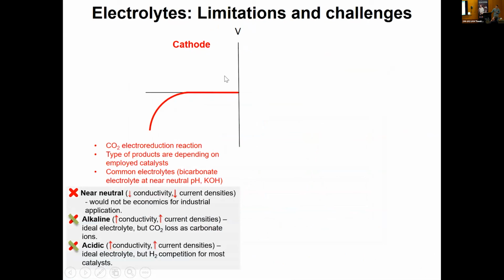So if you look at the limitations and challenges on the reduction part, where the CO2 reduction happens, near-neutral is mostly not economic for industry because it has low conductivity and low current density. If you want to compete with the established methods, that's a challenge. But alkaline electrolyte really shows good high conductivity and high current density. It's actually an ideal electrolyte, but we have carbon dioxide loss as carbonate ions. I'm going to show later an example of this, which we found, and which other research has also found. If we use acidic, as I mentioned earlier, with pH lower than 4, then we actually have an ideal electrolyte that can keep the carbon dioxide. But there's a strong hydrogen competition in this case.